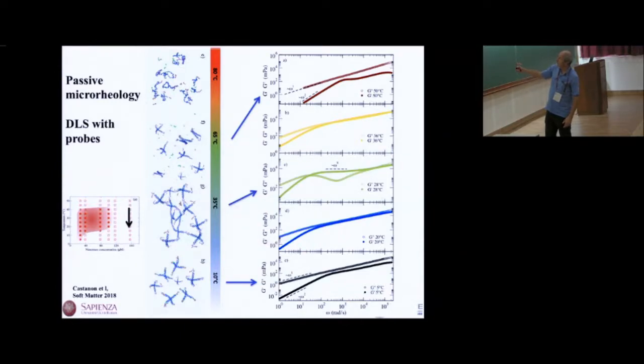You start from a typical liquid-like behavior. Then we go to a case in which we have selected the temperature where G prime is equal to G double prime in a large frequency region, and that's a usual indication of a percolation transition. You have clusters of all different sizes here. Then you go to almost a plateau, which is essentially a signature of an elastic behavior. This is the gel. Now the gel melts again through a percolation transition. Again, they become identical. And then you go to low temperature, and you get again the same type of behavior that you have at high temperature. So again, fluid, gel, fluid, through a percolation transition.